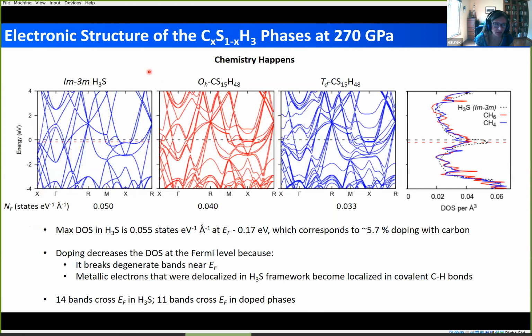So next, if we take a look at what happens to the electronic structure in these systems, we see here on the right-hand side the density of states of H3S. Then what happens when you have these octahedrally or tetrahedrally coordinated systems, the density of states at the Fermi level actually drops quite dramatically.